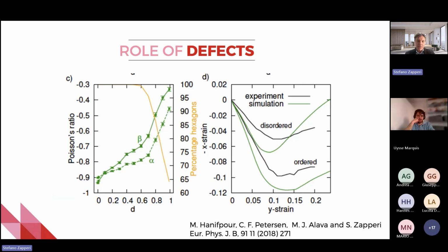But when you get loss of hexagons, then you start to lose these auxetic properties in a much stronger way. So this paper just tells you that disorder is bad for you. You start from a very nice auxetic material in the perfect lattice. You distort a little bit the geometry, you get less auxeticity. You distort the topology, it's even worse. So topology is more important than geometry and so on. But it's all a negative story, if you want. Disorder doesn't help.